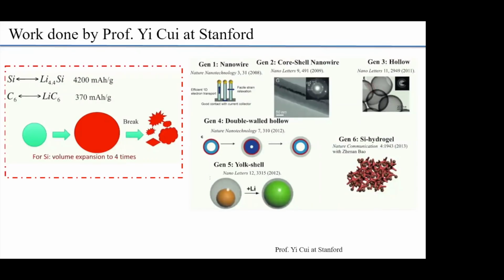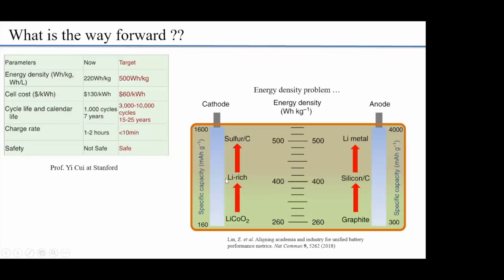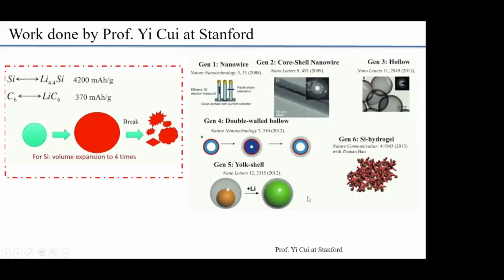Mm-hmm. So the last few slides, I want to dedicate to silicon and carbon hybrids, we talked about this one, right? There's been an amazing amount of work by Professor Cui and many other groups around the world. The premise is that graphite, represented by C6, takes 6 carbon atoms to host 1 lithium, and the theoretical capacity is about 370. But silicon, on the other hand, can host 4.4 lithium for 1 silicon atom, which is incredible. So the specific energy goes through the roof, like 4,200 milliamp hours per gram. It's more than 10 times.